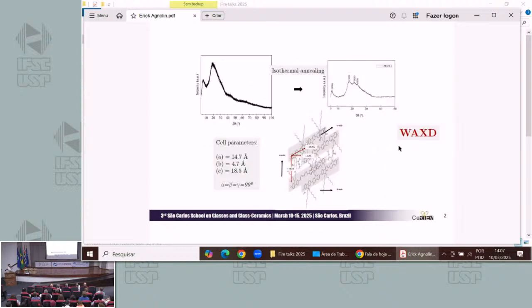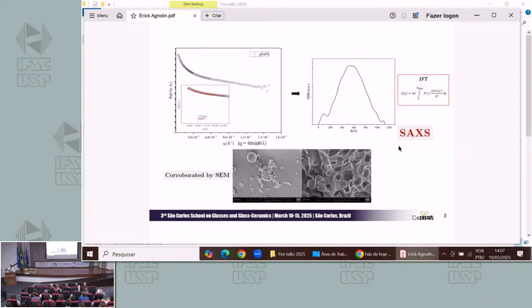Despite it having a very amorphous XRD pattern, we were able to give it unit cell parameters in an orthorhombic unit cell. And by doing SAXS analysis, we were able to predict the shape of the scattering centers, and also by doing an inverse Fourier transform of the scattering data, we obtained the size distribution histogram of these scattering centers. And this was, of course, corroborated by electron microscopy.